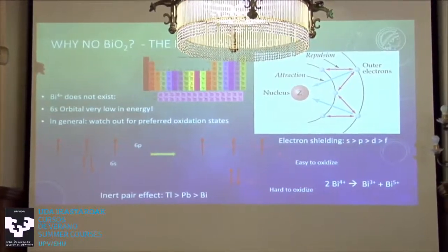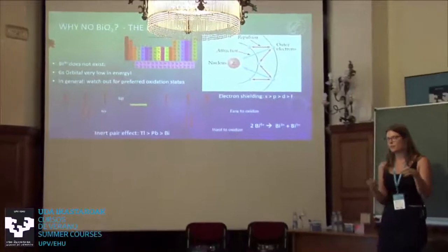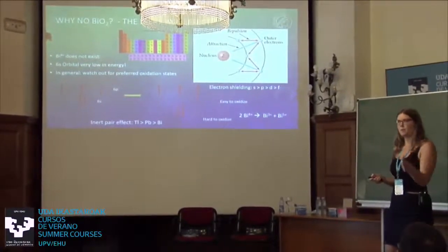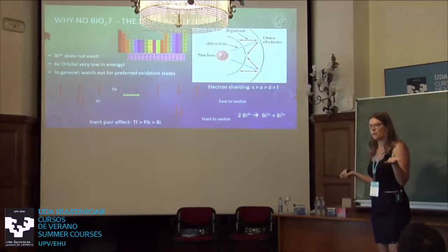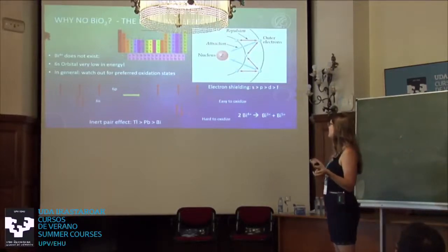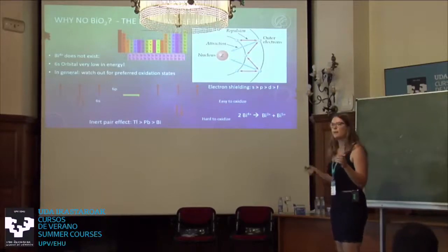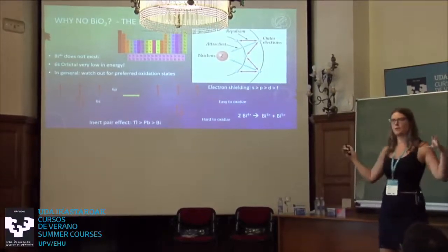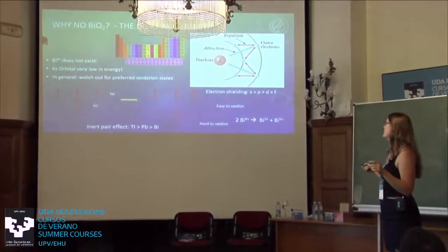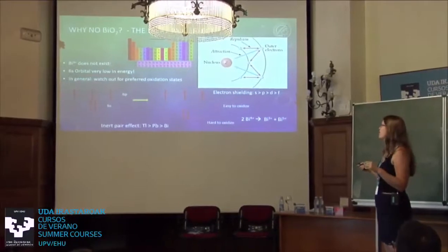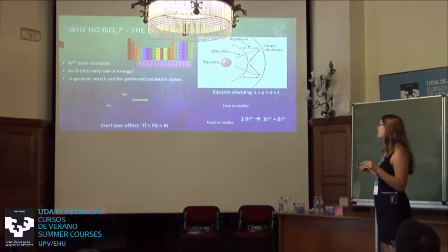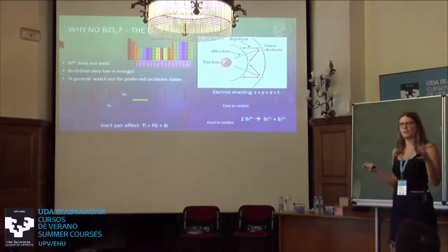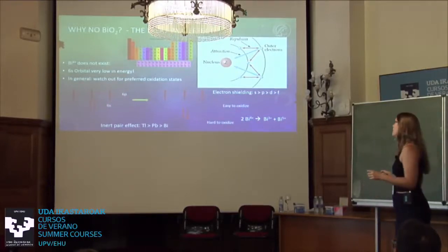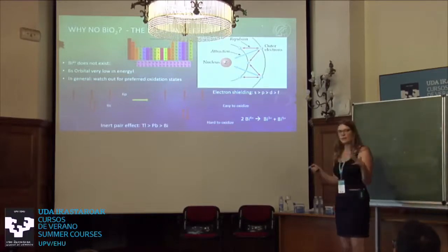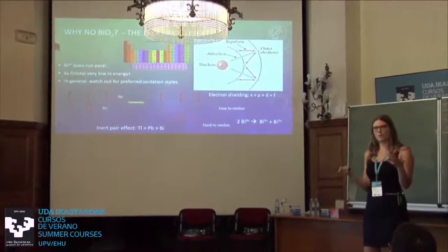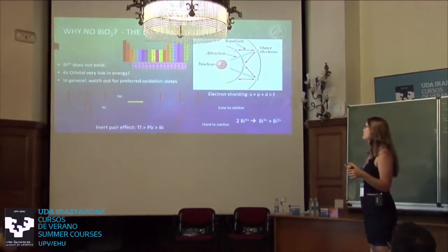And so if you have electrons in an S shell, they shield each other really well from the nucleus charge. But if you have them in a P or D or other shells, they don't really do the job as well anymore. And so if you come here and you start adding F electrons in a lanthanide, the shielding gets worse and worse, and this is why the atoms contract along this lanthanide row. So they get smaller and smaller. And also, for example, if you go to this part of the periodic table between zirconium and hafnium, you basically have the same size, although you add a complete new shell. And the reason for this contraction is that the electrons feel the nuclear charge more predominantly, and then if you come to this part of the periodic table where bismuth is,